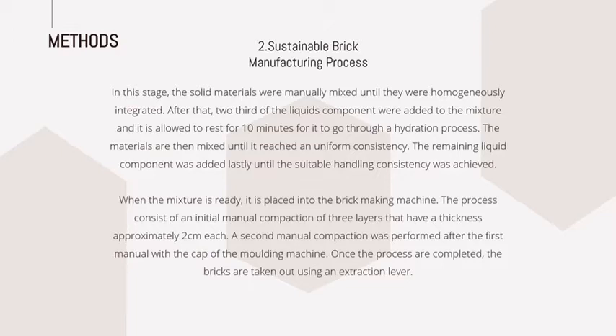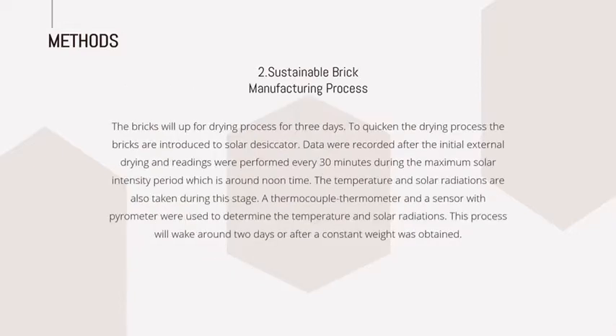The process consists of an initial manual compaction of 3 layers with a thickness of approximately 2 cm each. A second manual compaction was performed after the first with the cap of the molding machine. Once the process is complete, the bricks are taken out using an extraction lever. Next, the bricks are left out for a drying process for 3 days. To quicken the drying process, the bricks are introduced to a solar desiccator.